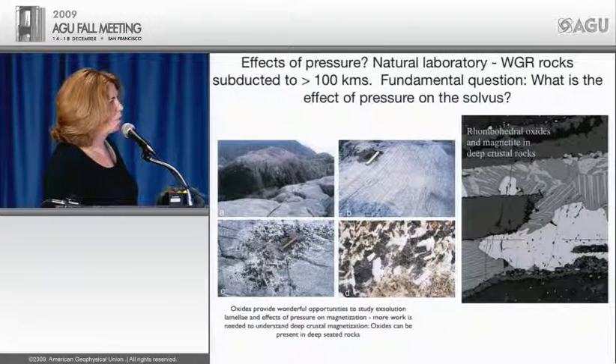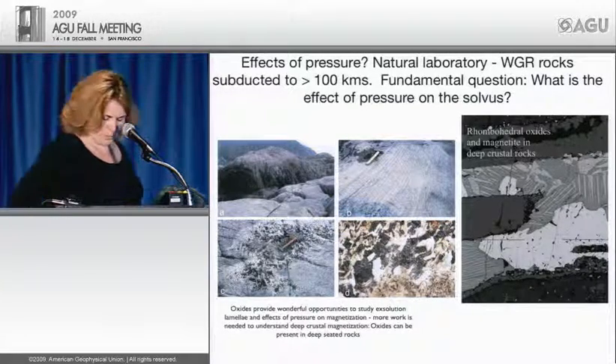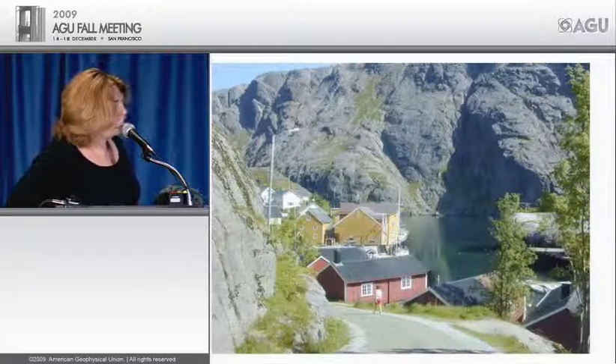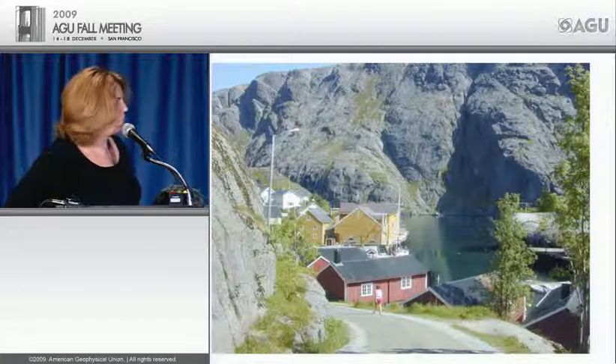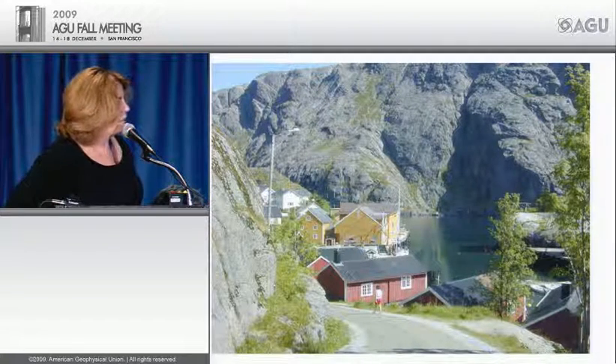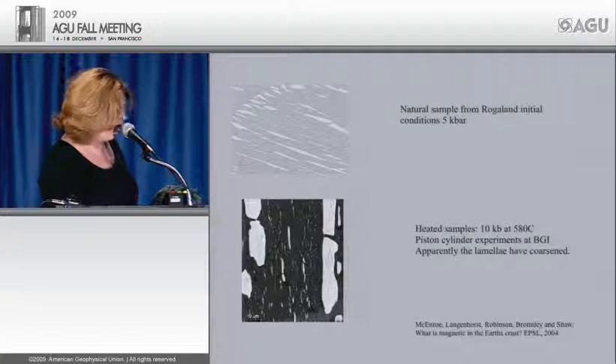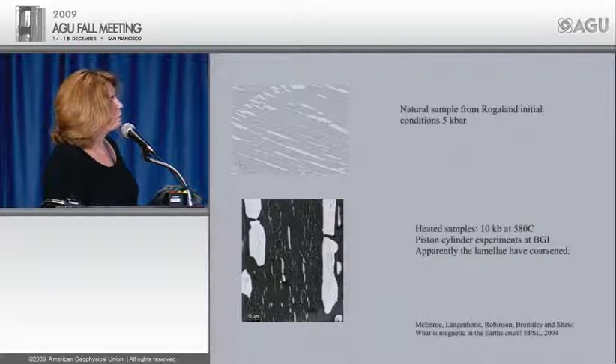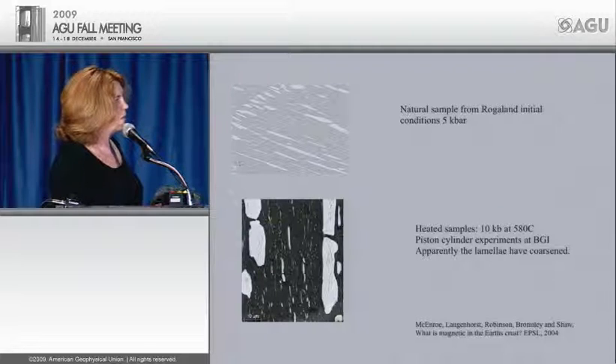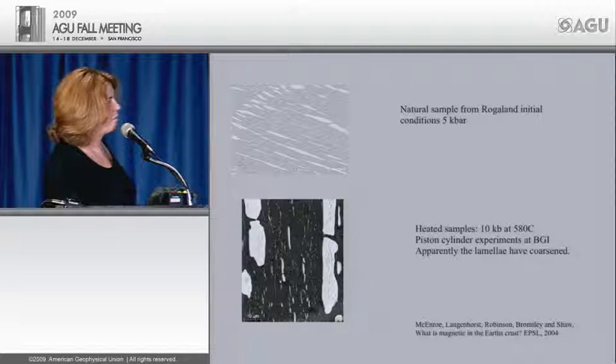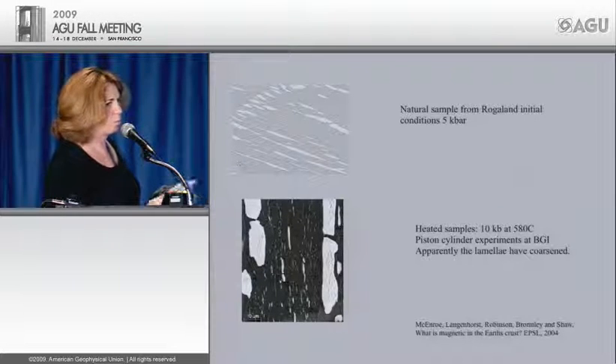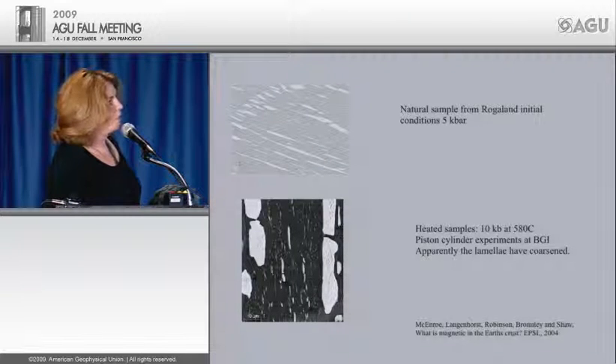And also, what's the nature of the magnetic material? Now, to look at this, we're going to actually move down to Rogaland again, to where we find the hemoilmenites that we're working with there. And so the question they had is, are these lamellae stable down at 580 degrees, or are they reabsorbed? And if they are stable, then they're going to contribute to magnetization at depth in the crust.